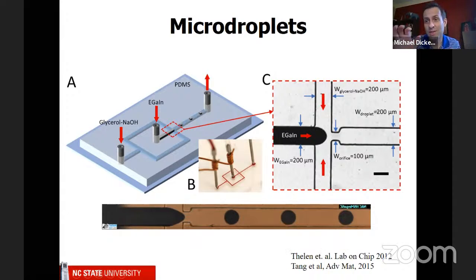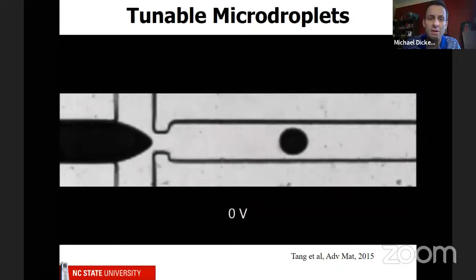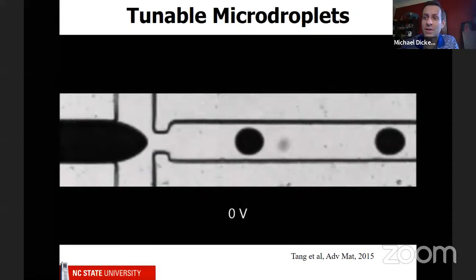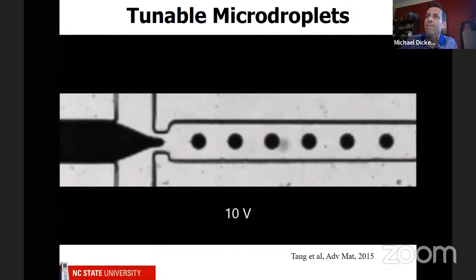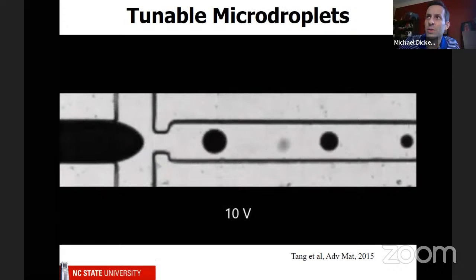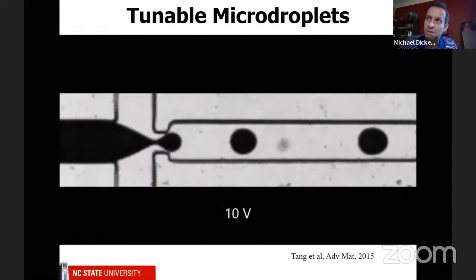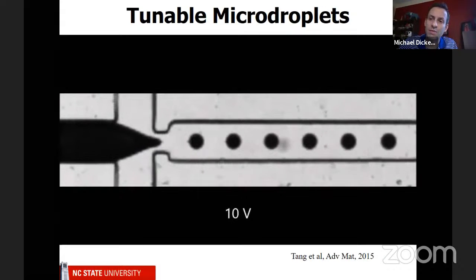And one way to change the size of these droplets is by changing the flow rates. But I can tell you from experience, whenever you change the flow rate, it takes about 10 minutes for it to come to some new steady state, because all the pressures and stuff get out of whack. Well, in this case, what we do is use voltage instead to control the surface tension. So when we apply 10 volts to the metal, we lower the tension, and we can form smaller droplets. And then at 0 volts, it goes back to high surface tension, and it forms bigger droplets. And so you can do this in real time.